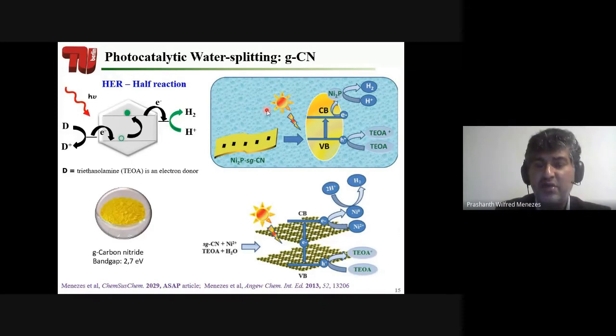We have done some of this work using carbon nitride as the photocatalyst, this semiconductor. And what we did was we introduced nickel phosphide nanoparticles on the surface of the carbon nitride, shown here with the black dots. We can quench the holes, take the electron to the nickel phosphide, and use those electrons from nickel phosphide to generate hydrogen. We also did more experiments with nickel salts, and they're very efficient. This is a very good strategy to produce hydrogen. However, as I said, we cannot produce oxygen from the system as we are quenching those holes.